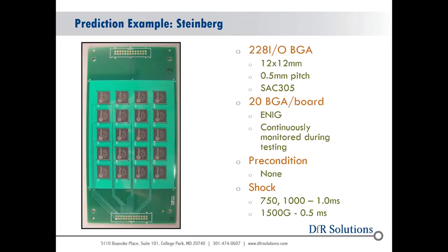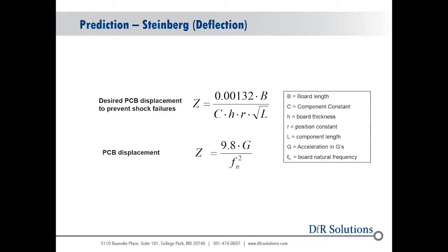So if we look at the prediction for Steinberg for shock, it's not straightforward. It is a fairly complex calculation, because you have to predict, you compute out the Z. I should put some subscripts on here. There's a Z critical. That is the critical displacement, which I don't want to exceed, because if I exceed it, I'm going to have a failure. It's just an empirical equation that I'm showing here, 0.00132 times the board length, a component factor, the thickness of the board, position constant, and again, we're assuming that the board shape during the shock event follows usually a sine cosine type of function, and then the square root of the component length.